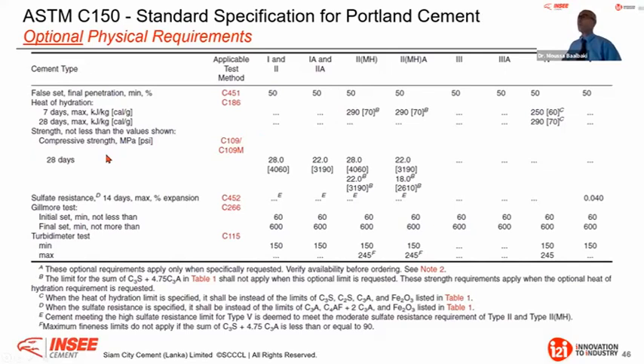Now, in terms of compressive strengths, again, there is a limit, but it is very, very close to what is physically required. Now, in terms of sulfate, you see they have a sulfate resistance test at 14 days, and they tell you here it is required only for type 5. Type 5 is the high sulfate resistance OPC based. And for the other types, it is mentioned here that cement meeting the high sulfate resistance limit of type 5 is deemed to meet the moderate sulfate resistance requirement of type 2 and type 2 moderate heat. Therefore, you have to fulfill this.